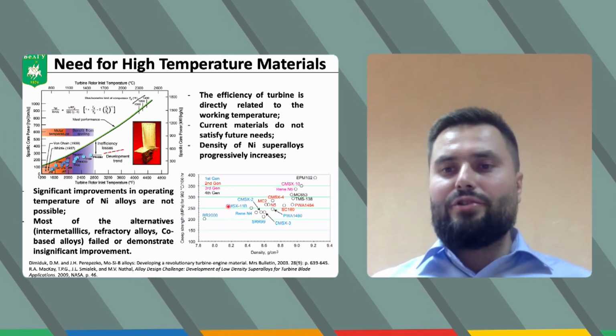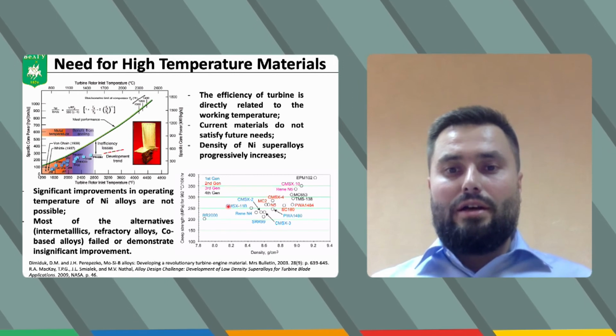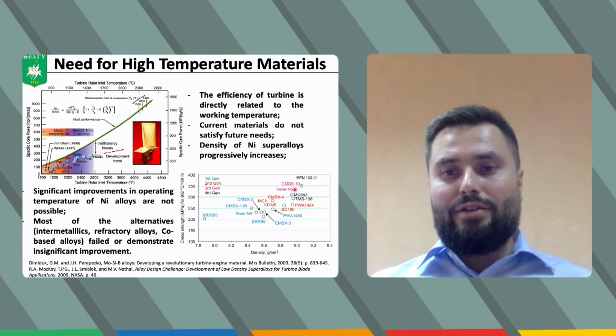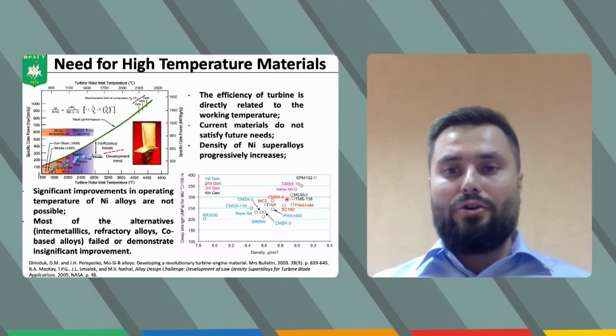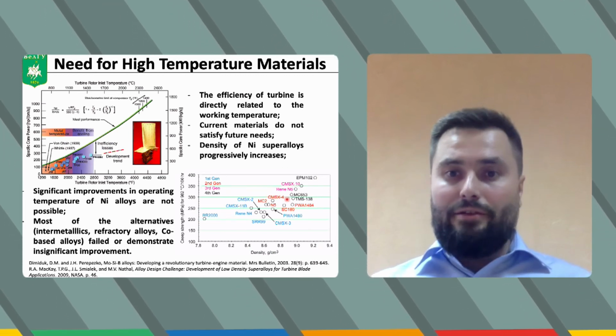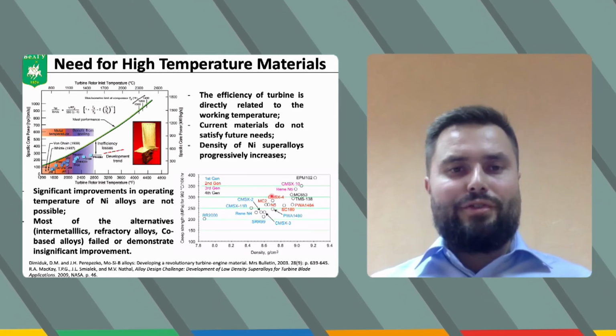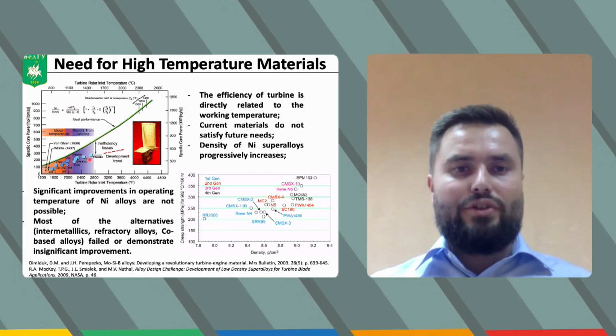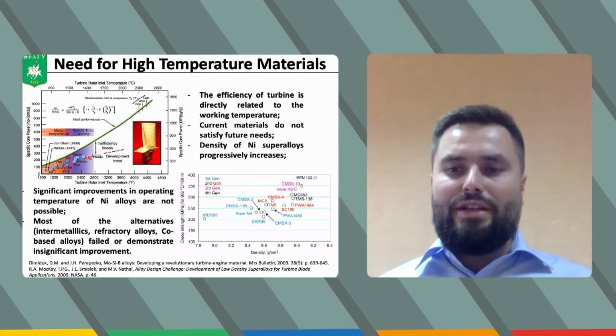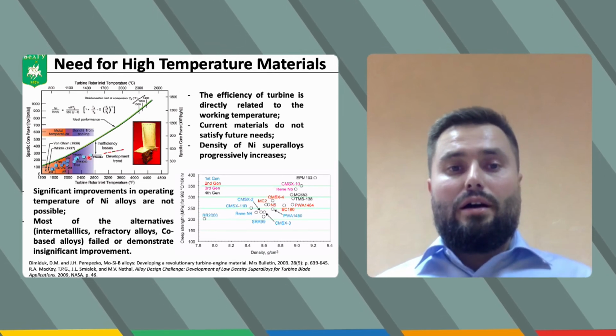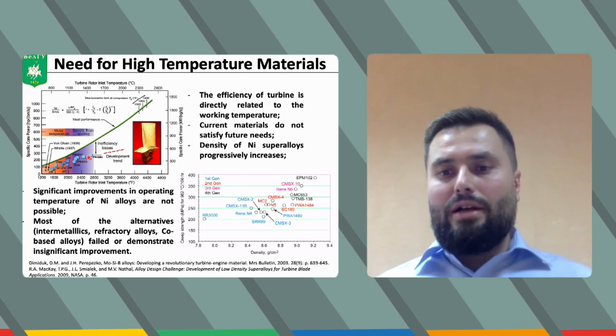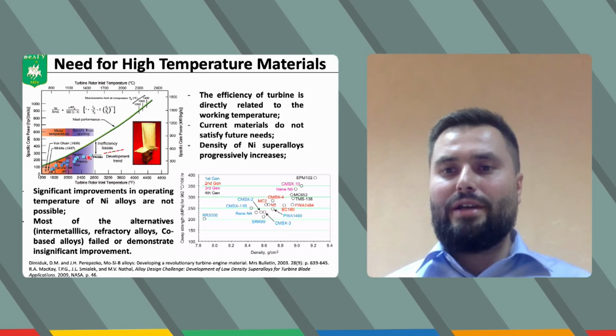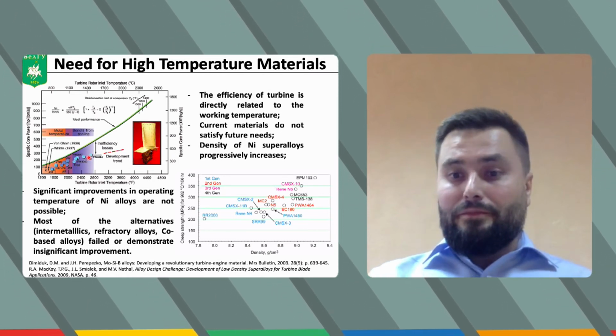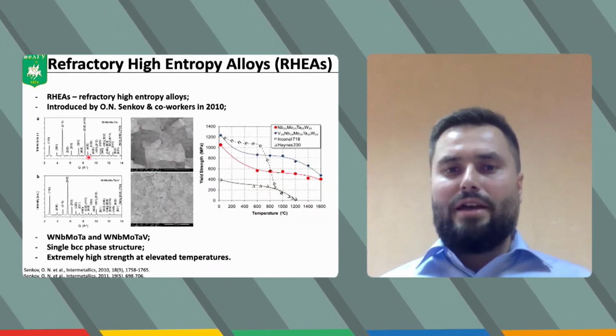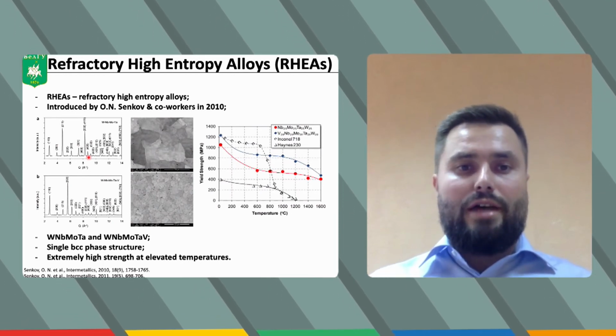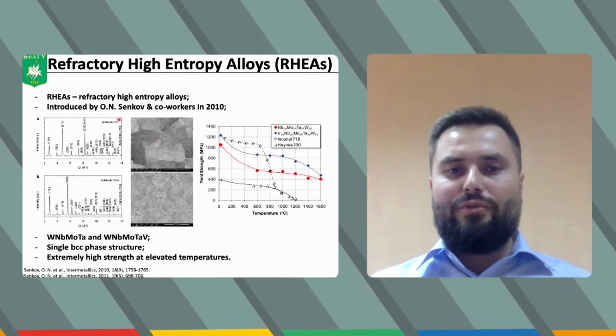Moreover, to increase the high temperature strength of these alloys, some quite exotic strategies were applied during alloying. For example, the recent generations of the nickel-based alloys have utilized a lot of rare earth elements, which are very heavy and dense. And these, of course, made the alloys themselves heavy, and that resulted in some loss in efficiency of the engines. And for, I think, at least 2 or 3 decades, researchers around the world were searching for a potential substitute for these nickel-based alloys, but unfortunately, none of the considered alternatives was found to possess the required combination of properties. And in recent years, the so-called refractory high entropy alloys have attracted a lot of attention in this regard. And here I am showing you the results from the first couple of publications on the topic.